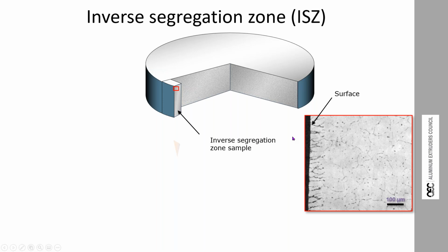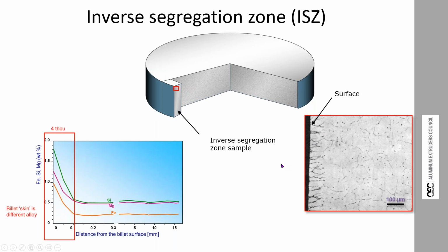If we cut a slice from one, and we cut a slice from the slice and a little piece, and we look really tiny right down here in the outside edge skin of the billet, we have this inverse segregation zone that Danny mentioned. If we plot the chemistry, that 4 thou area there on the surface, the chemistry is much, much higher. The silicon's 4 or 5 times higher. The iron's 5 times higher. So the chemistry of this layer in the surface is very different.